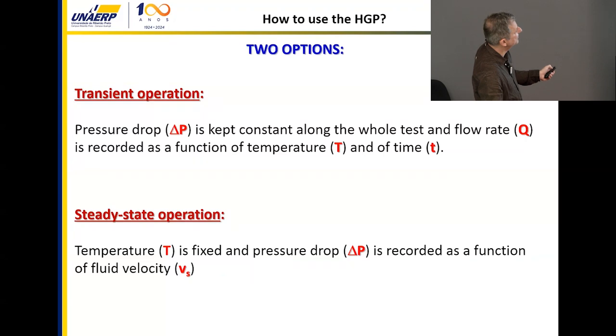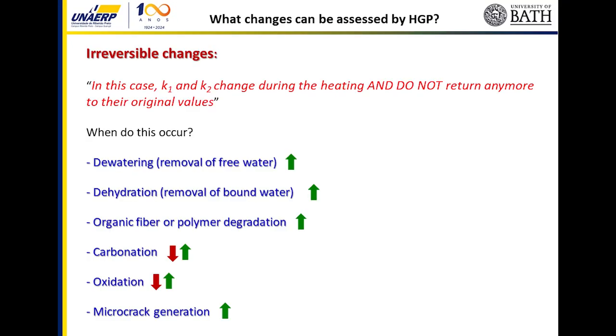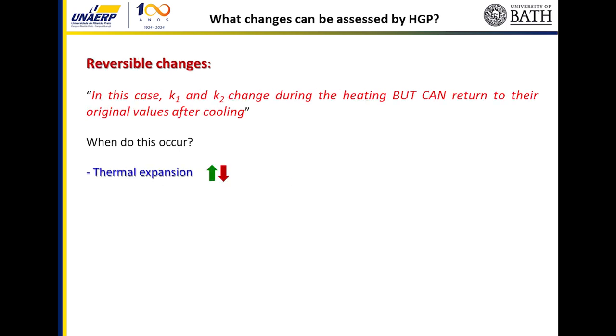We have two options to operate, the transient operation and the steady state operation. In this case, we keep constant the pressure and see the signal of flow on the other side. In the steady state operation, we put a pressure and measure the flow rate. What we can get from this technique, for example, dewatering or removal of free water, dehydration, organic fiber or polymer degradation, carbonation, oxidation, microcrack generation, all these events we can track inside the material using this technique. And these are irreversible changes, but we can also have reversible changes, which means thermal expansion.